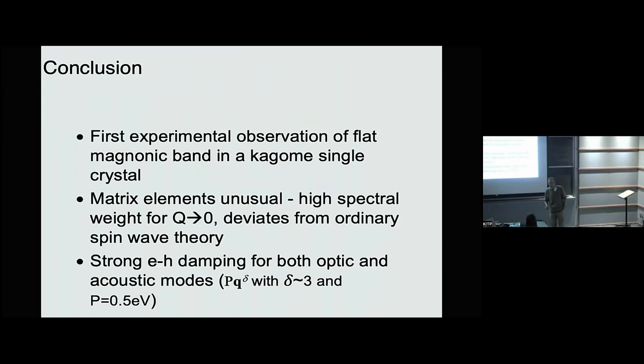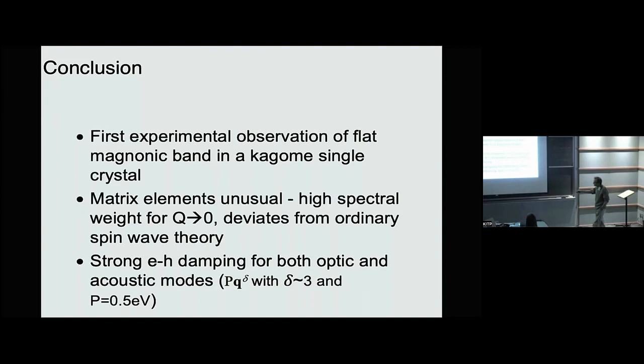In conclusion, we have provided the first experimental observation of a flat magnonic band in a Kagome single crystal. The matrix elements are very unusual — there is a high spectral weight for Q going to zero, which deviates from any conventional spin wave theory. We suspect this is connected to the strong electron-hole pair damping which we see for both the optic and acoustic modes. But we have to figure out how to get the angular momentum to come out in the long-wavelength limit when we decay away from the conventional spin wave. Thank you very much.